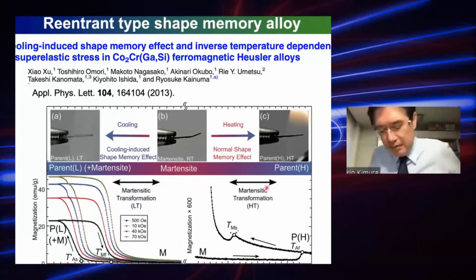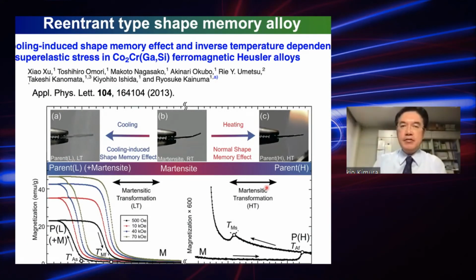So now I mainly want to talk about the reentrant type shape memory alloy, which is shown by the cobalt-based Heusler alloys. This actually shows the cooling-induced shape memory effect, which was reported several years ago by Professor Kainuma's group. You see a Martensitic phase transition from high temperature to low temperature. This is actually the same as in nickel-based compounds. But you see again the transition to the cubic phase at lower temperature. Then I would like to say this transition is a reentrant type transition.